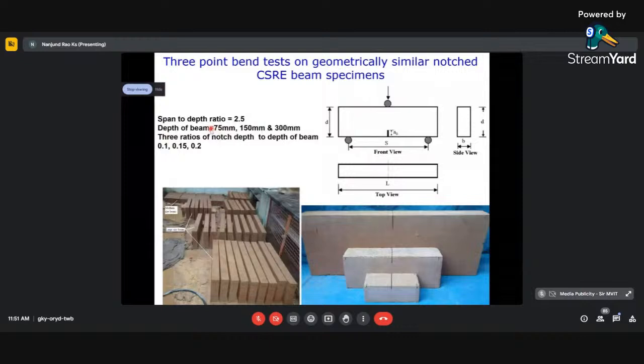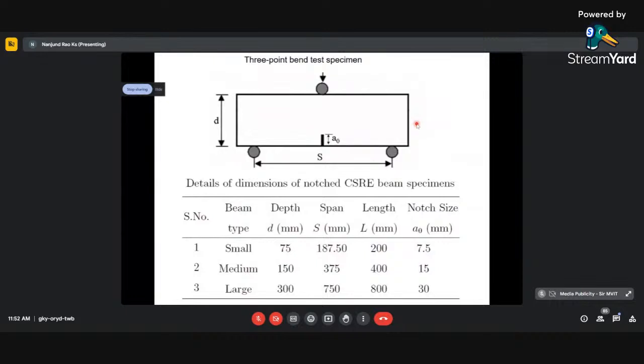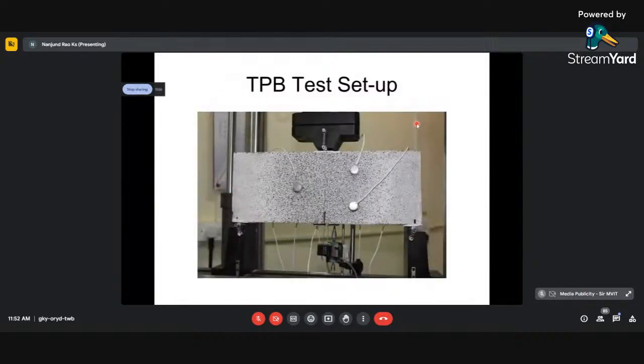So the parameters of the beam, specimen dimensions, and the notch depth, different notch depths that we use for understanding the fracture properties, which later can be used in analytical models. These are the dimensions of the specimen. These are typical tests under progress. We use the DIC technique to get the deformation information, and for the damage which is inside, which is not visible, we use what are called acoustic emission sensors 1, 2, and 3.